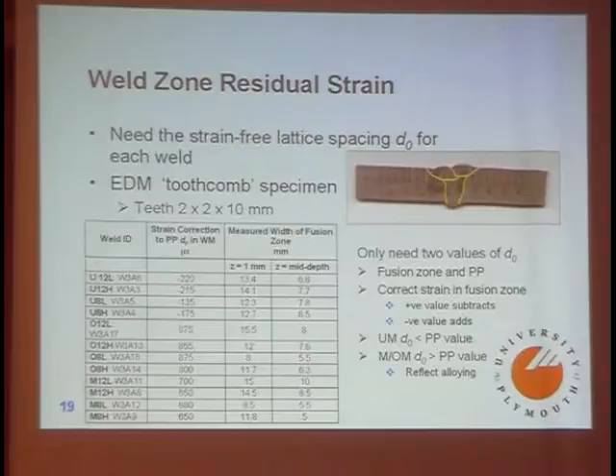And I had originally hoped that there wouldn't be too much variation in the D0, the strain-free lattice spacing, in each weld. It turned out that was utterly untrue. As you can see here, these are the corrections to the parent plate D0 microstrain in the various weld conditions. They range from a correction of plus 875 microstrain to minus 220 microstrain. So this becomes very important to take account of.